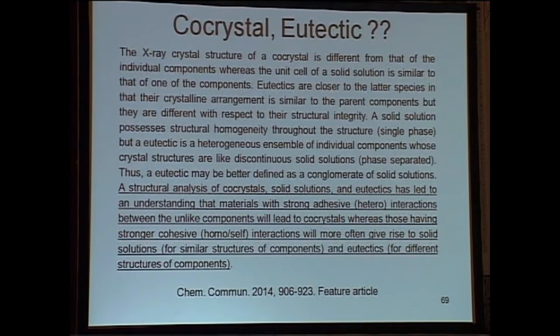So this is where the idea of solid solution also comes in, and that's why I thought I'll bring in all those topics. The X-ray crystal structure of a co-crystal is different from that of the individual components, whereas the unit cell of a solid solution is similar to one of the components. Eutectics, we believe, and that's the philosophy we have advocated in this review article, are closer to the solid solution in that their crystal arrangement is similar to one of the components, but they are different in terms of their structural integrity because there is a second component.